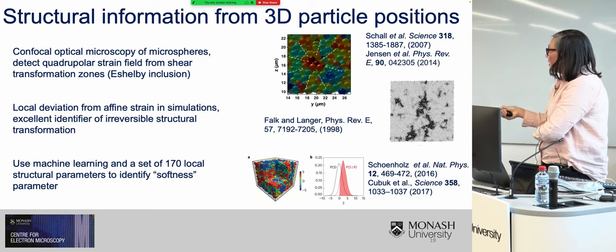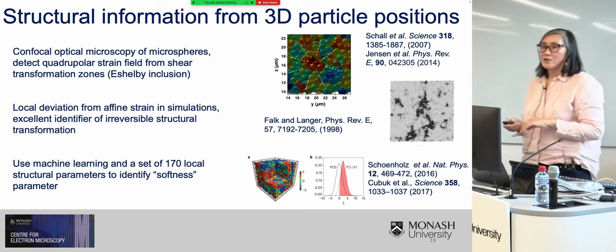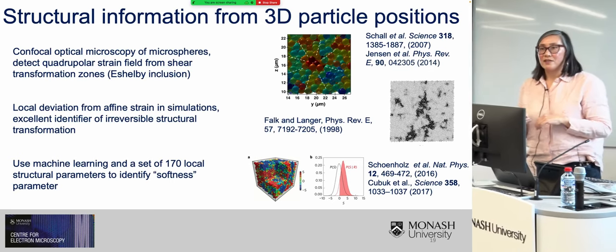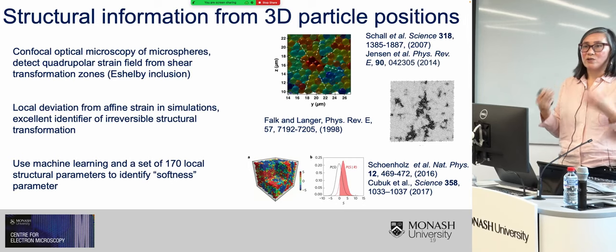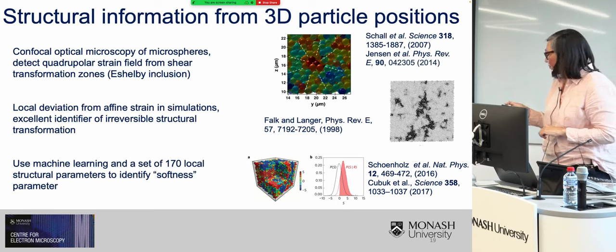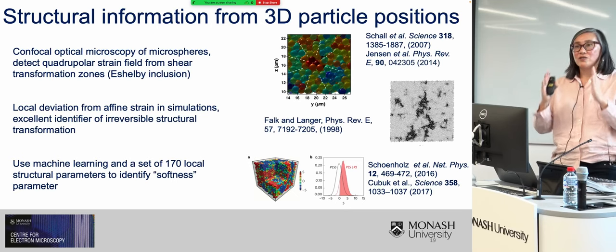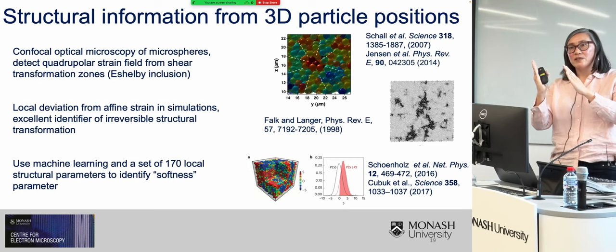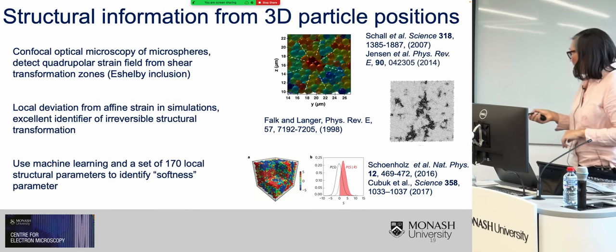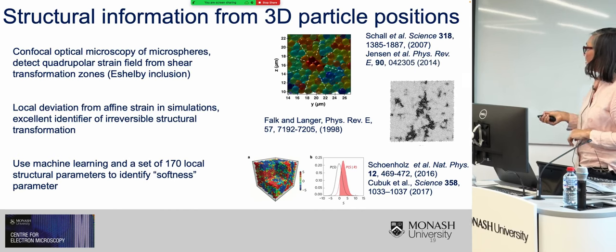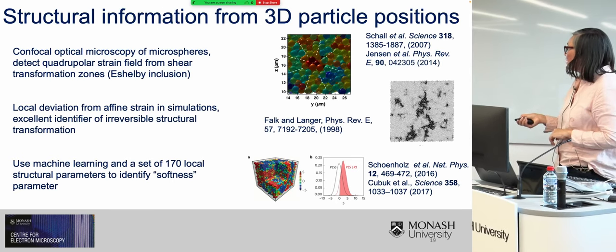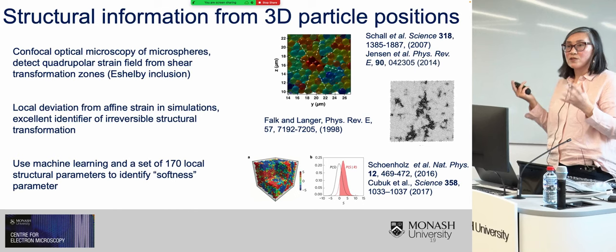Which is quite nice. Here in these simulations, people have looked at the local deviation from affine strain and reported that this is actually quite a good signifier of a transformation which is irreversible. And by affine strain, I mean the movement of particles in the same magnitude and direction as the applied strain. Here also, people have used machine learning and a set of 170 local structural parameters to identify a kind of softness parameter.